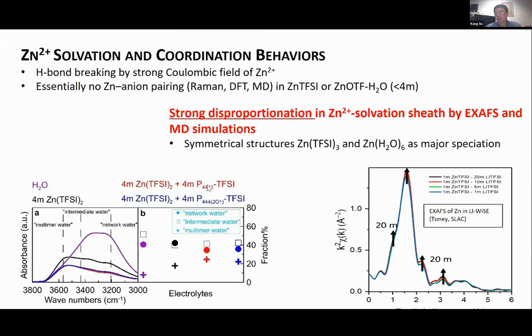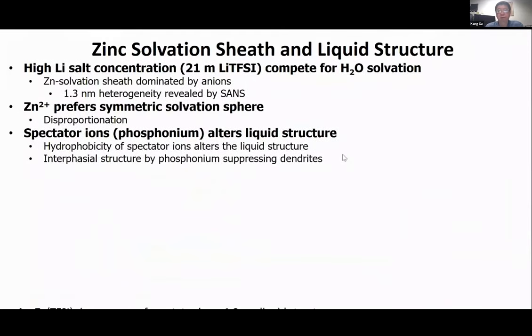That means in the TFSI solution, no matter what concentration you have, most of the zinc solvation environment is either completely TFSI, 3 of them, or 6 water molecules, which is a sort of octahedral symmetry environment. There's no mixture of those two. You don't have one TFSI and 4 water molecules. The exact reason we are still not sure, but that seems to be very true and very reproducible.